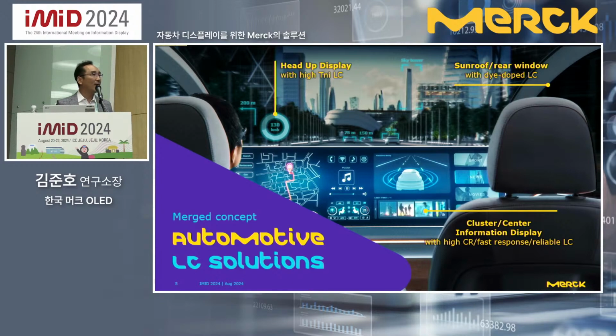Because the HUD is located just under the front window, the temperature goes much higher than other displays in a car. So we are developing the LC with high TNI. And for cluster or CID, obviously we need high contrast ratio and also fast response time and reliable LC with various temperature for clear picture.